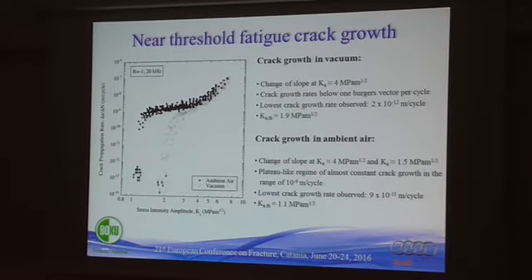Well, then I come to the results of the fatigue crack growth measurements. Crack propagation is plotted here with solid symbols for crack propagation in ambient air. Open symbols are crack propagation in vacuum. Due to very high testing frequency, ultrasonic fatigue testing is restricted to the near threshold regime. And as you can see, the threshold stress intensity in ambient air is significantly reduced due to this plateau-like regime of almost constant crack growth in the range of 10 to the minus 9 meter per cycle.